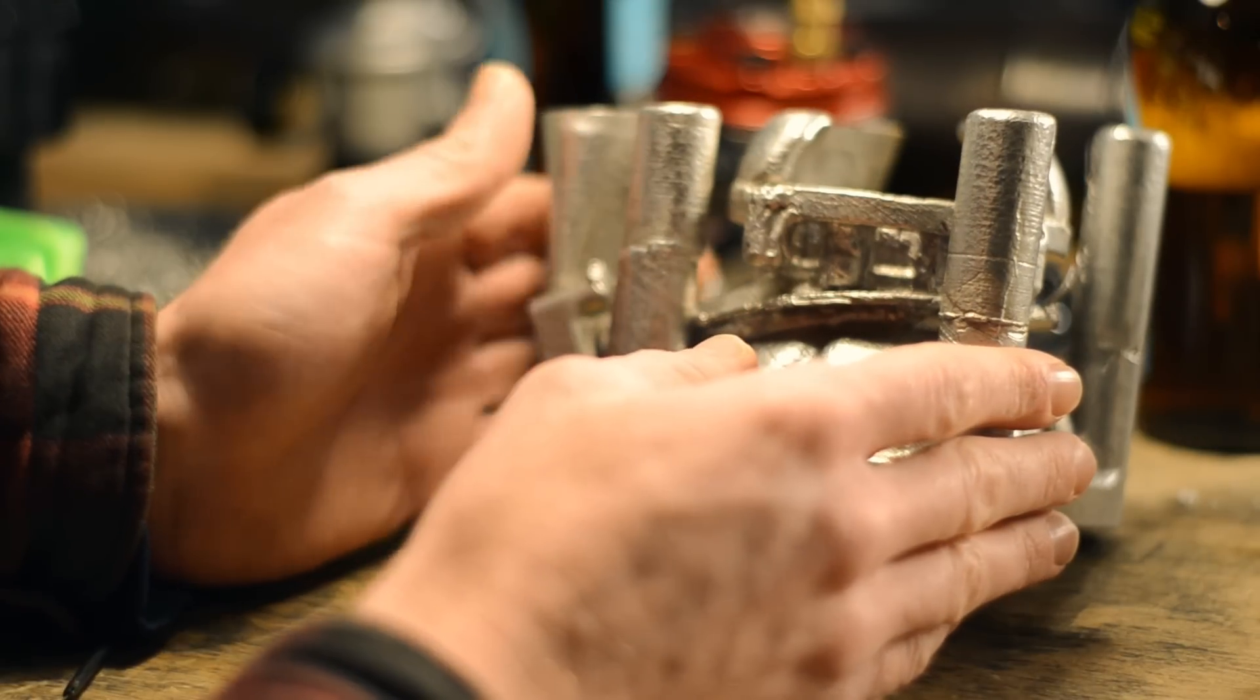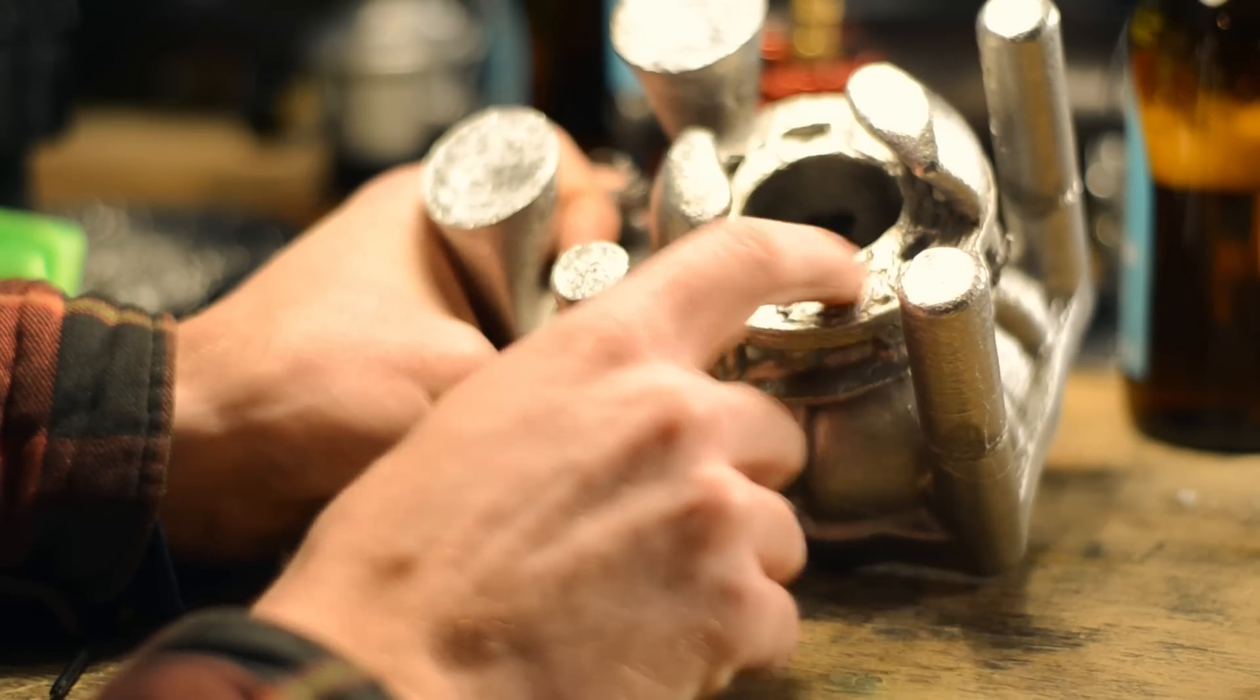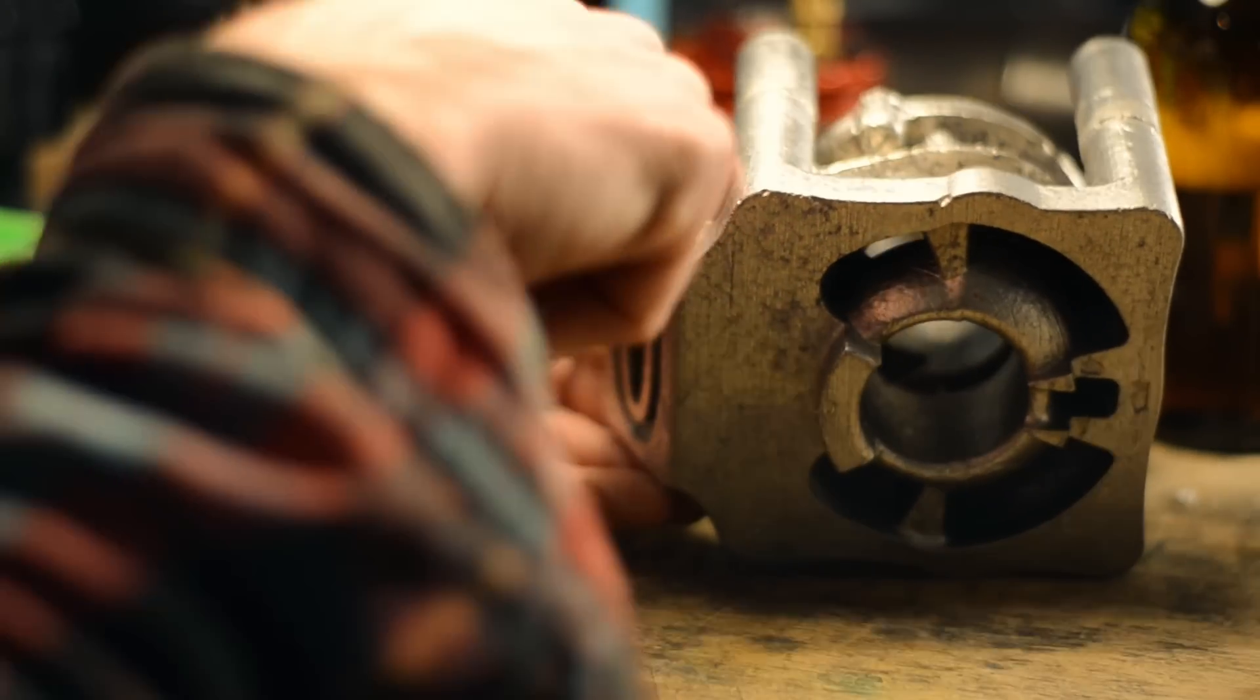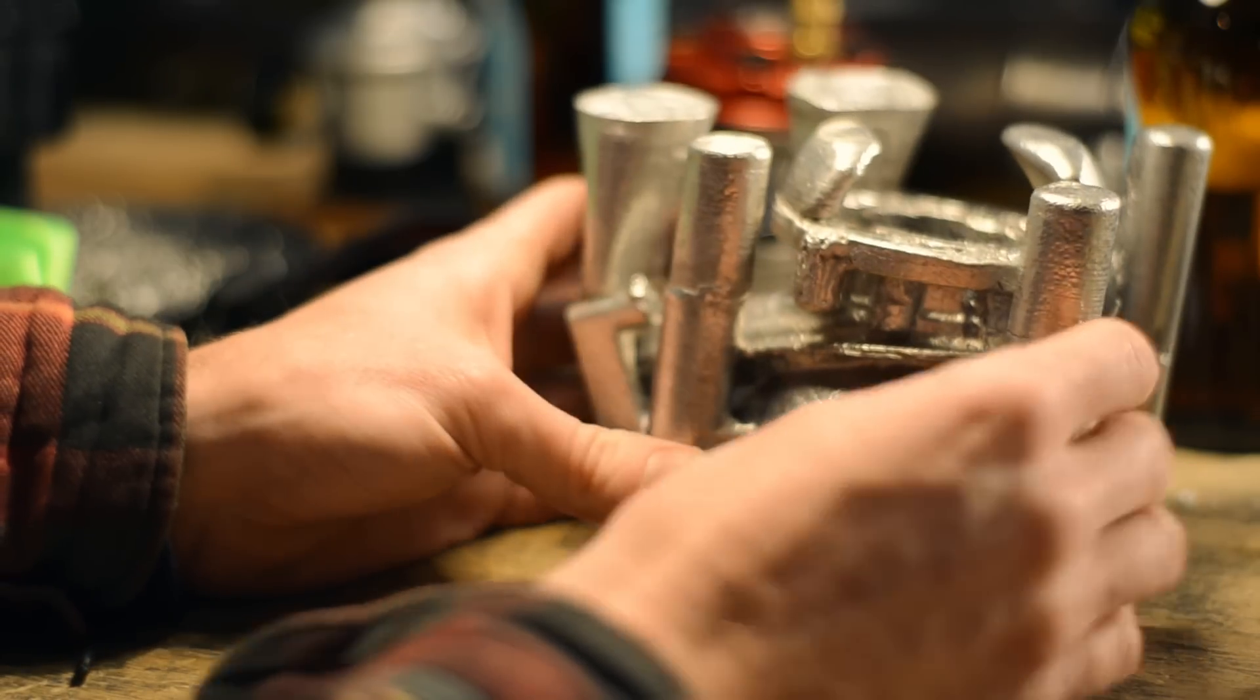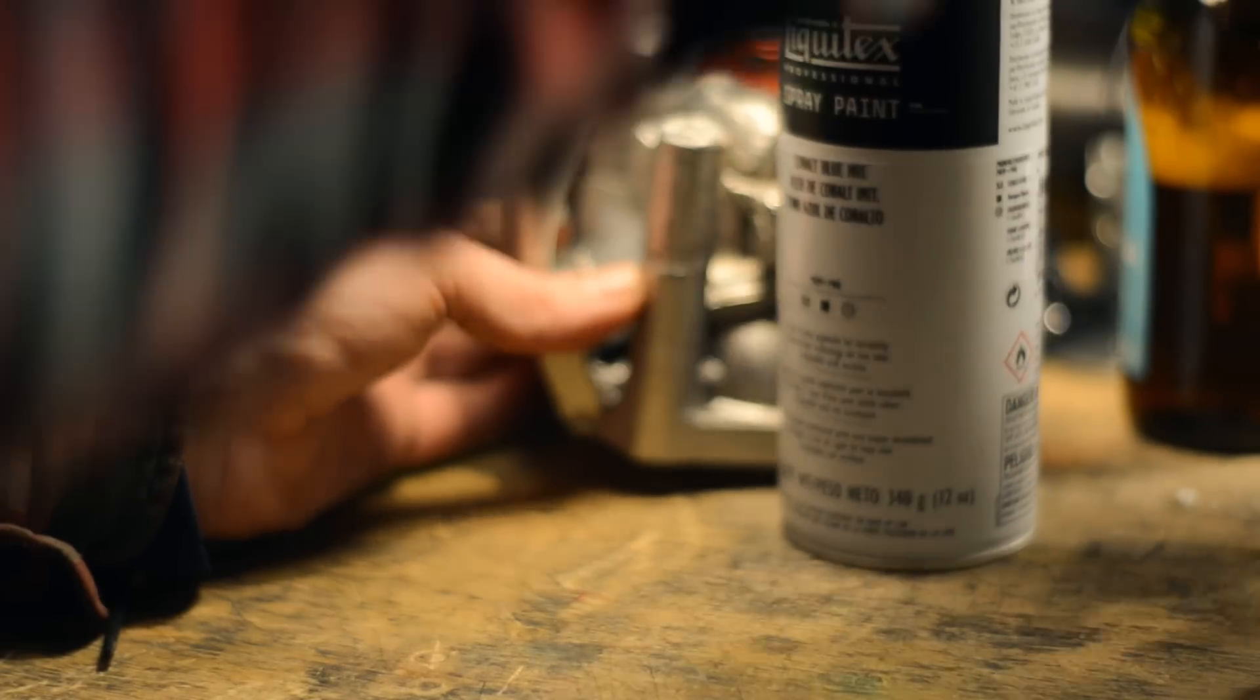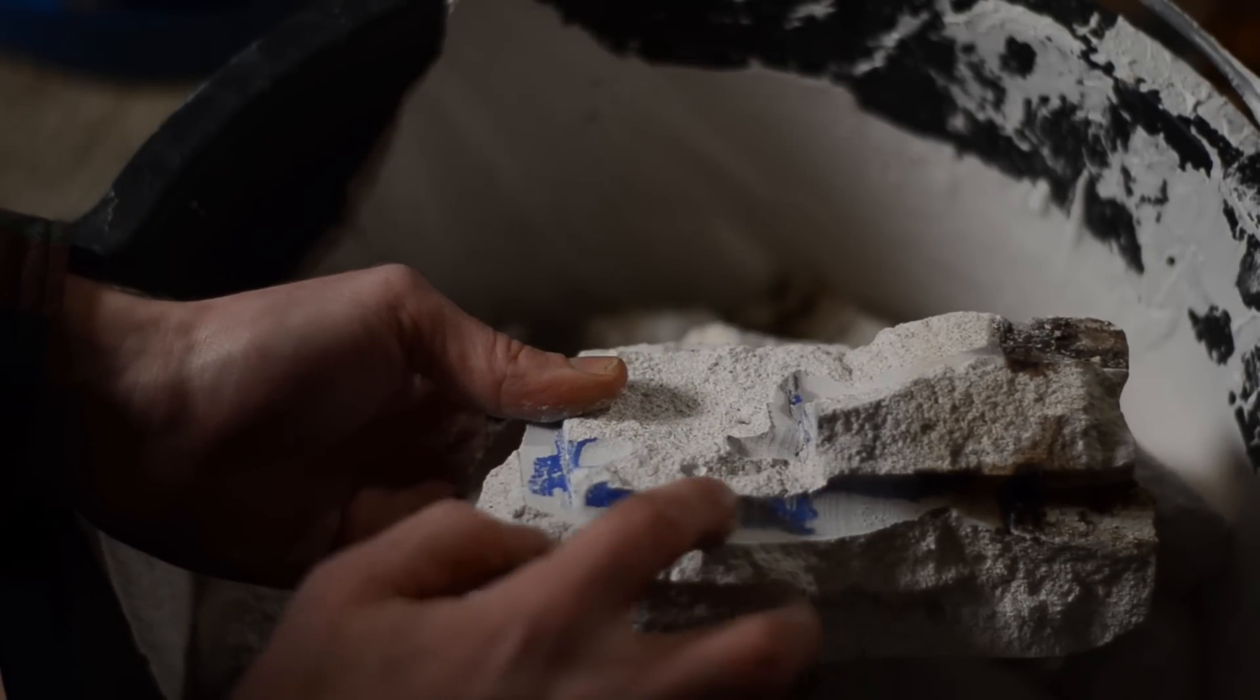Also I think maybe some of these weird worm tracks and holes up here, and there's a lot of them under the exhaust ducts too and also inside of the cylinder here, might be caused by gassing from that acrylic paint I used. Parts of it actually survived the molten metal, and the same color was present after the casting when I broke the mold.